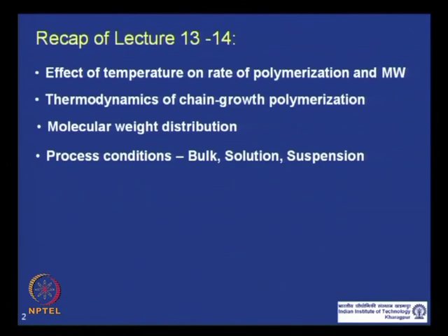We talked about the ceiling temperature and the relation between ceiling temperature and the monomer concentration at equilibrium, and then we talked about the dependence of monomer structure on the values of delta H and delta S, the enthalpy change and the entropy change, and how those values depend on the structure of the monomer, depending upon how the double bond in a monomer is stabilized or the polymer is strained or not.